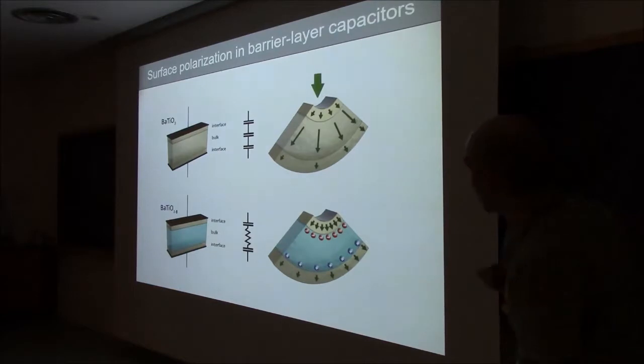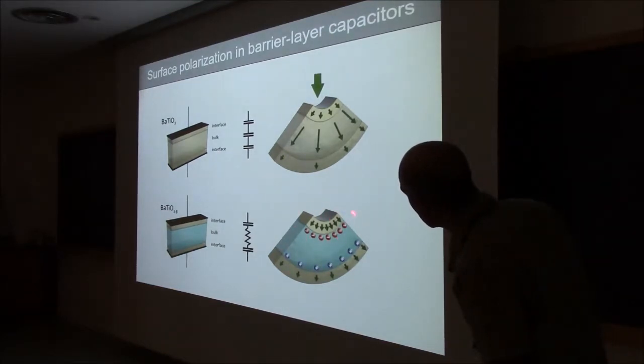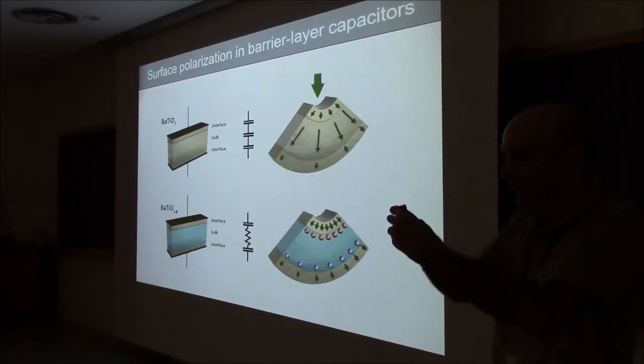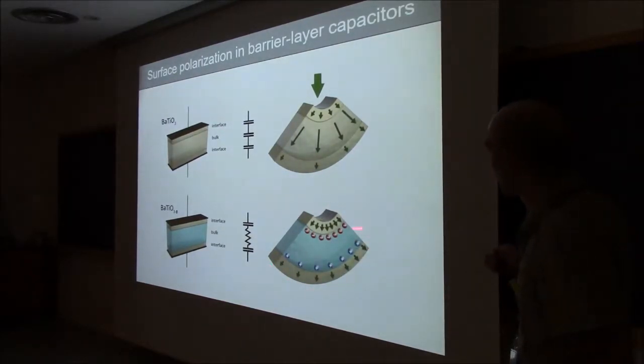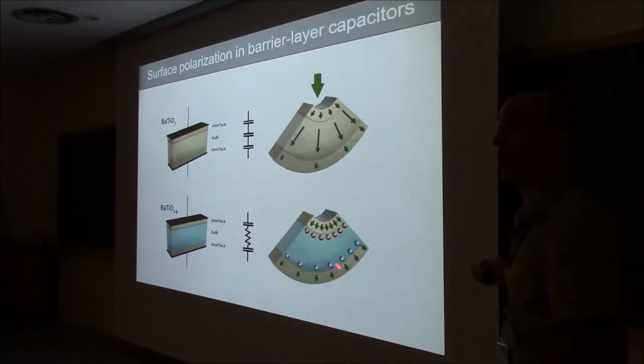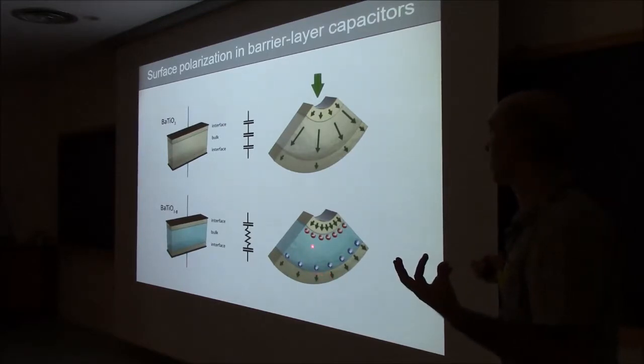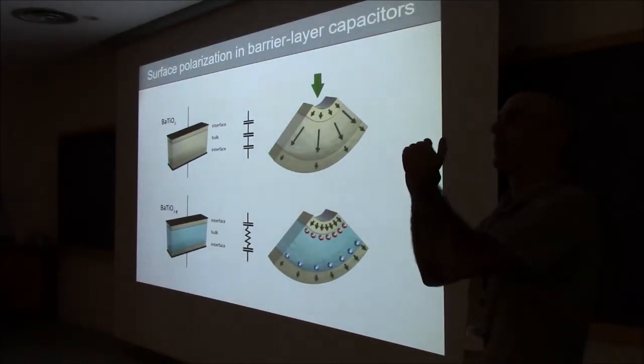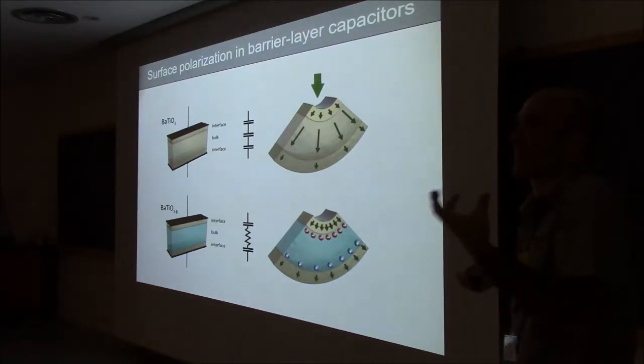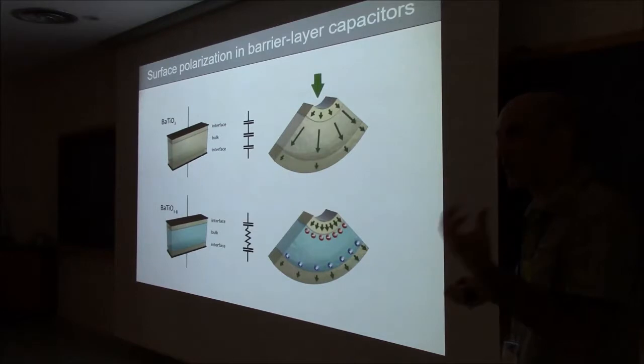But also, and that's important, when the surface piezoelectricity tries to polarize, so you are stretching the surface here, you're compressing it here, the surface is trying to polarize. Now it can do so very cheaply because there's a lot of free charge that can screen the polar discontinuity. So whereas here the polar discontinuity imposed some limit as to how big the surface piezoelectric polarization could be, now that limit is no longer there. The surface piezoelectric contribution can be as big as it needs to be.